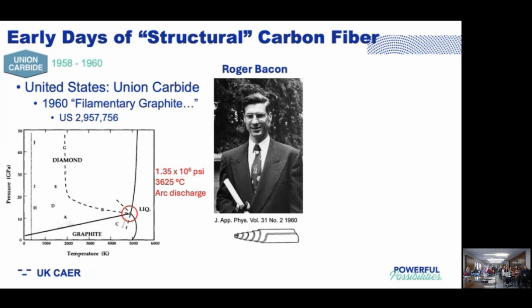So he was working at an incredibly high temperature, something on the order of 3,600 degrees C, achieved by doing arc discharge—running current through graphite electrodes, striking an arc at extremely high temperatures, albeit very transient, but under extremely high pressure. I think this was high pneumatic pressures of noble gases in this cell. When he took the cells apart, he noticed over and over that on one of the electrodes had grown all these whiskers of graphite.